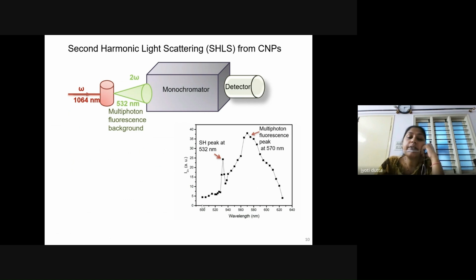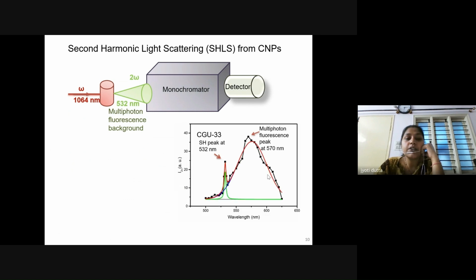Now, if we consider to investigate any one of these, either the second harmonic peak or the multiphoton fluorescence peak at 570 nanometer, we have to remove the contribution from the other peak. For example, if we want to investigate the second harmonic peak at 532 nanometer, we should eliminate the contribution from the multiphoton fluorescence peak at 570 nanometer and vice versa. So we have opted for a spectral fitting of these two peaks in order to remove the contribution of one peak from the other. So this is the spectral fitting which we have opted.